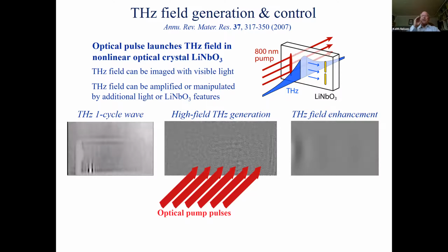We make them by using a short pulse of optical light to irradiate a nonlinear crystal. We use this crystal lithium niobate, others are available. And what this does is it actually shakes the ions around, and since that's moving charges around, a suddenly moving charge radiates. There's a burst of radiation that makes a single cycle terahertz pulse. And that can be visualized right inside the crystal.